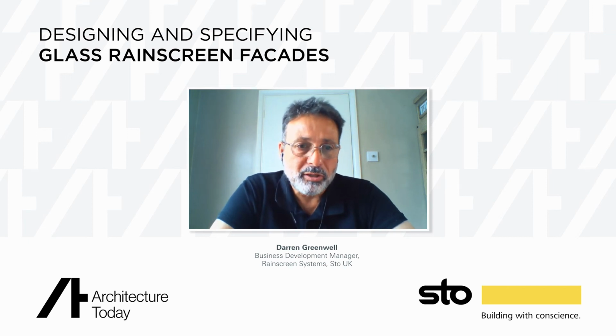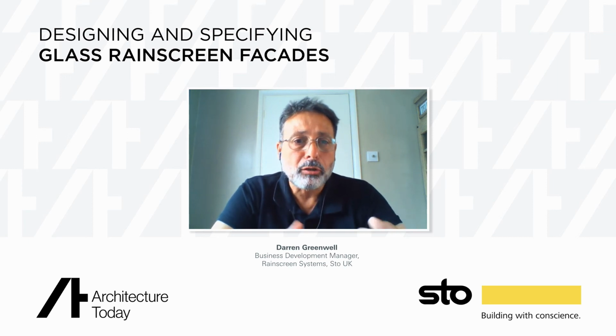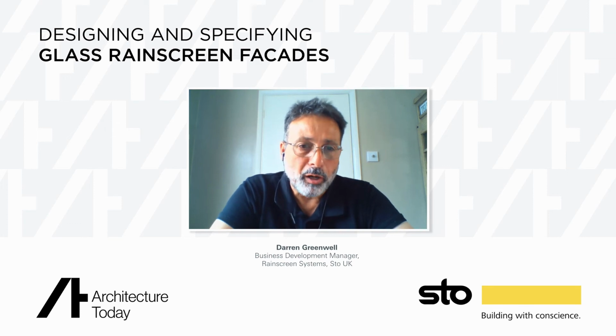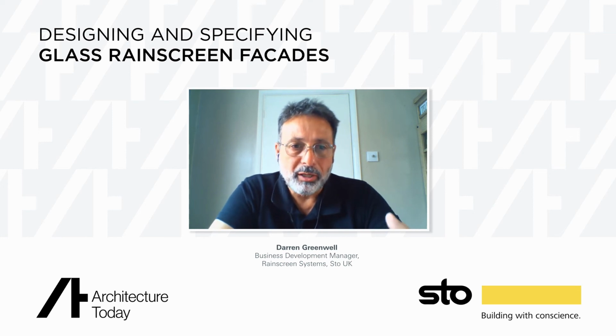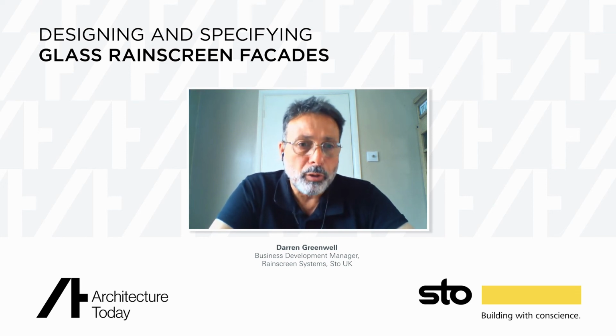In the first part of the presentation, we touched on the greenish hue that comes as a natural byproduct of the iron content within glass. So by going with a low iron type of glass, it gives you a much truer colour. If it's a white, you get a bright white as opposed to a greenish off-white, which is the standard.